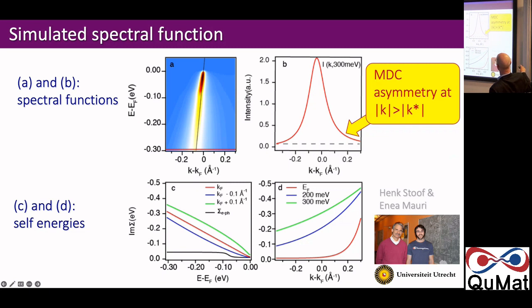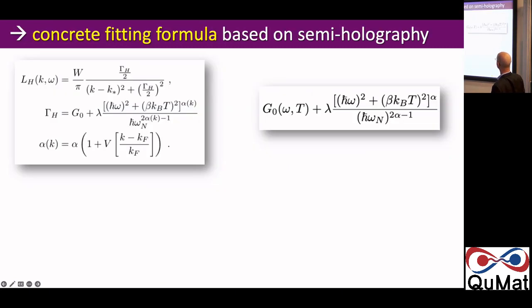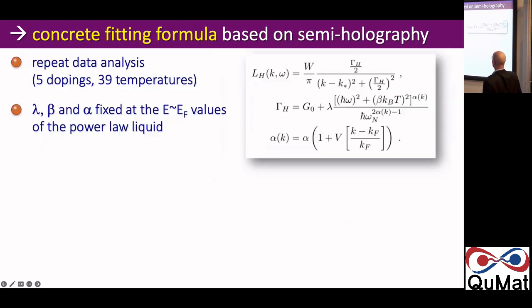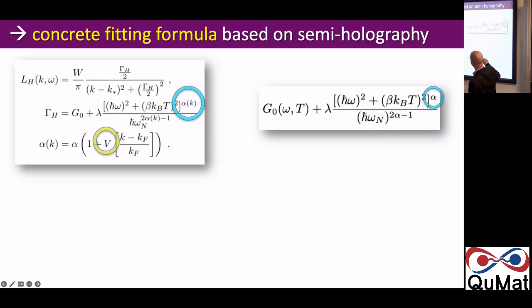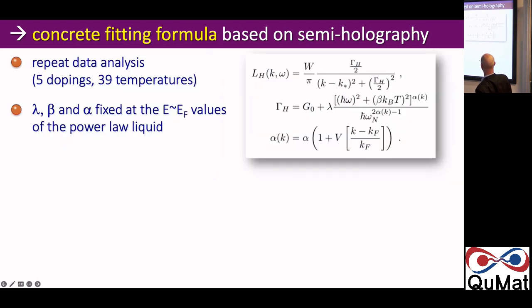So you see in their data also very clearly that the momentum distribution curves are asymmetric, just the same way as the experimental ones. So we needed a fitting formula we could use to really fit the experimental data, and that's the one that looks like this, with this alpha in it. And we have a parameter V, which should be 1 in their semi-holographic model, because it was the alpha outside 1 plus thing. And we'll see about that in a moment.